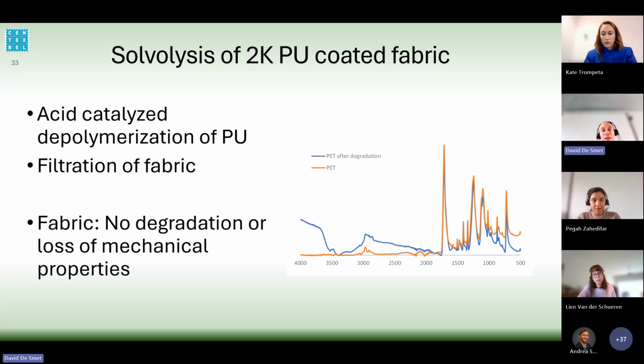Another end-of-life option, as mentioned, is to look at solvolysis, so chemical recycling. In this case, we give an example of solvolysis of a 2K PU-coated fabric. We did it in the case of an acid-catalyzed depolymerization in the presence of water. Afterwards, the PU was degraded, and you can simply recover the fabric by a filtration process. On the fabric, again, we did the same tests as discussed previously, and again here we didn't see any degradation issues or loss of mechanical properties.